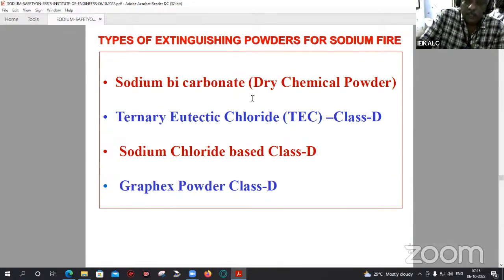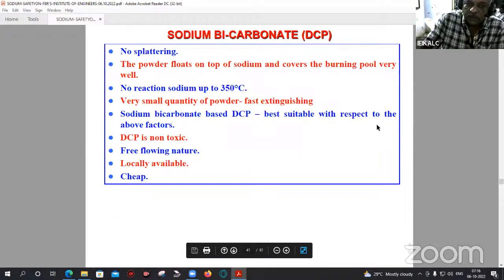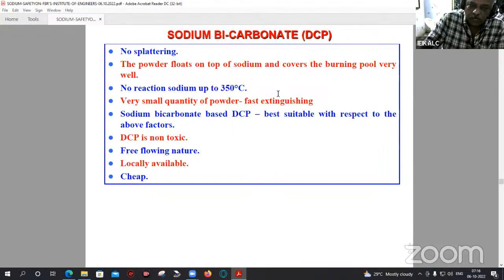Sodium bicarbonate, NaHCO3, was the standard sodium extinguishing powder. And these are some later developments like ternary eutectic chloride, sodium chloride based powder, and Graphex powder. Testing was done, and you can see the sodium bicarbonate was quite good. There was no splattering. The powder flowed. The density of the powder needs to be less. Density of sodium is 900 kg per meter cube, so the powder density should be less than that, for it to blanket the surface and cause oxygen starvation.